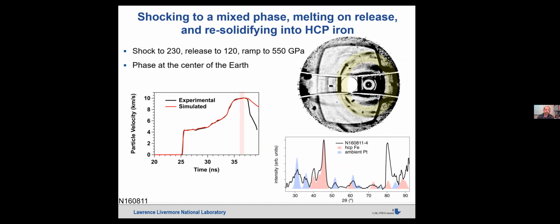So getting to some of the raw data, I'll go through a couple of examples of the data points and the different types of phases that we see. So the first thing I'll say is, this is not diffraction from an XFEL. This is not diffraction from a synchrotron. This is diffraction from a plasma source. And so a plasma source at 550 GPa. So I'm pretty proud of this data. But if you are looking at this with the context of seeing synchrotron data or XFEL data all the time, pull it back a little bit.